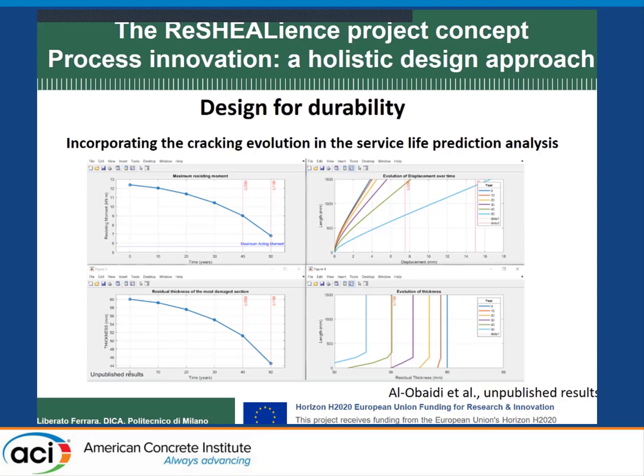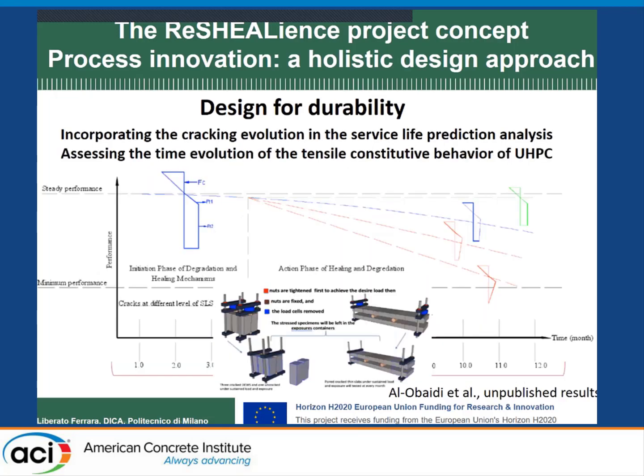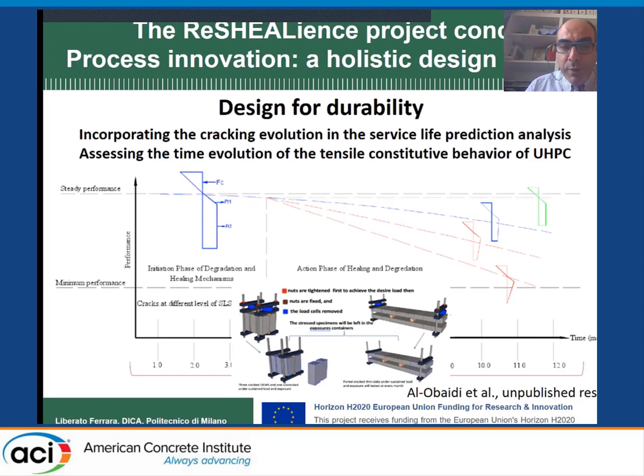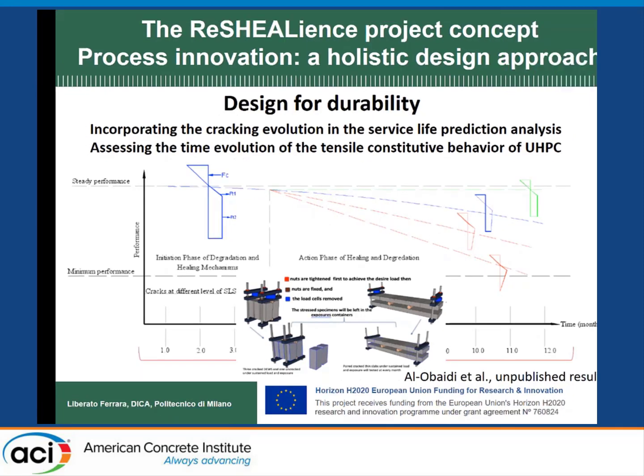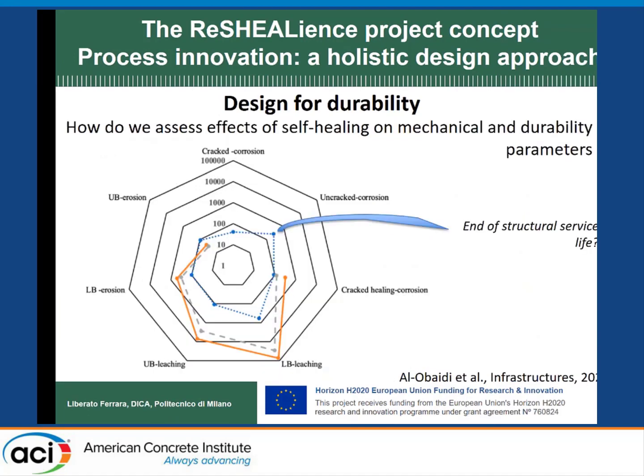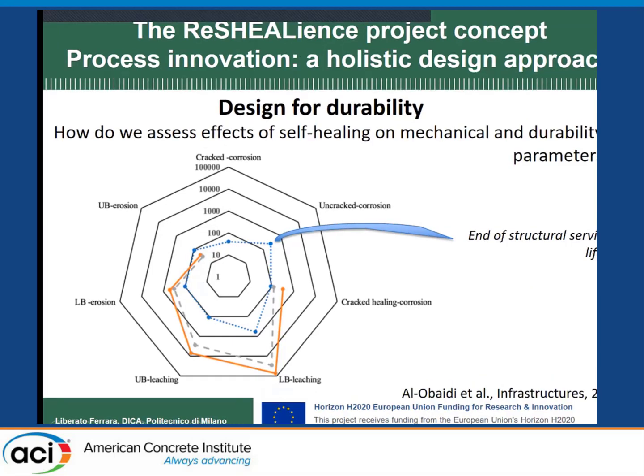And we are also validating these assumptions with a dedicated experimental campaign, quasi unique in the literature, where the material heals under load, which is quite unique because most of the results that you find are for material that heals with no load at all. So the results have been elaborated in this sense. This is a rosette diagram where you can compare the expected service life for different mechanisms: cracked or uncracked, healed, leaching, and erosion.